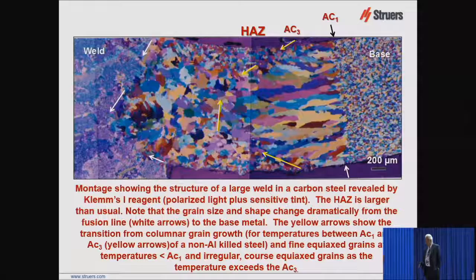Over here, look at the sharp interface here between the original base metal. Every grain is visible, and it's all equiaxed. This is the Ac1, and this line here, so to speak, is the Ac3 temperature. Above the Ac3, we're 100% austenite, right? And in the two-phase region, because it's not aluminum killed, we've got columnar grains. And this is not aluminum killed. I know that because I had the chemical analysis of the heat.